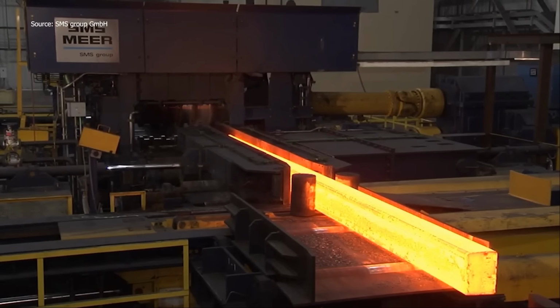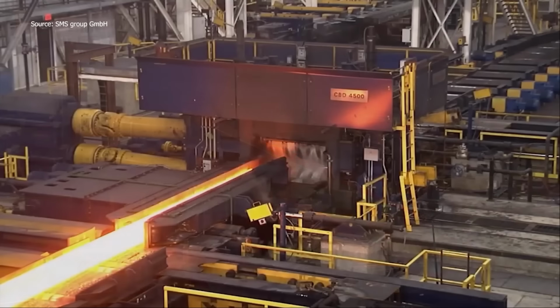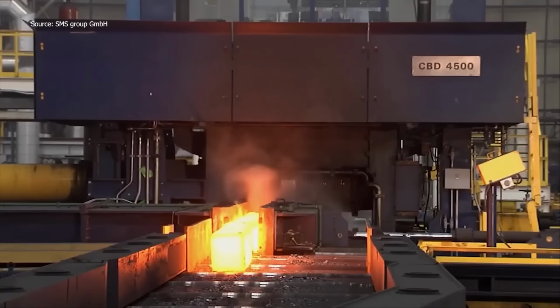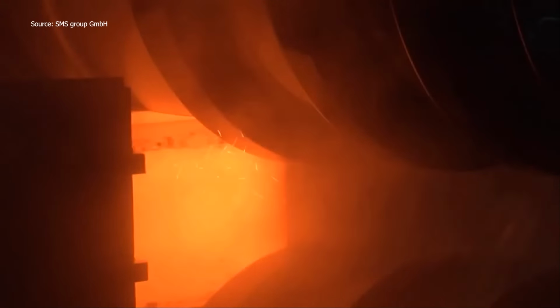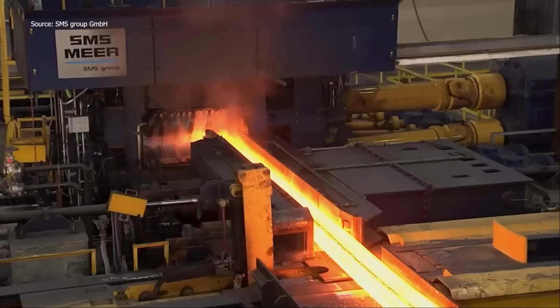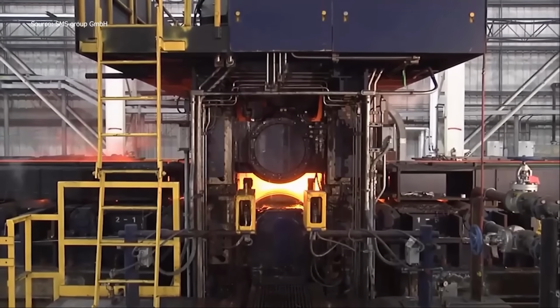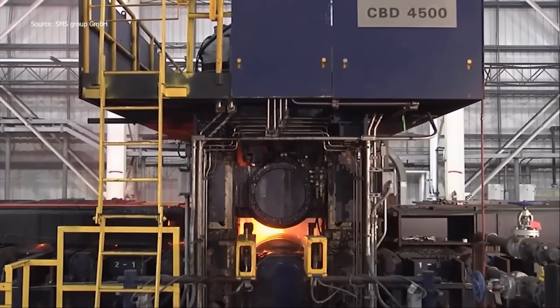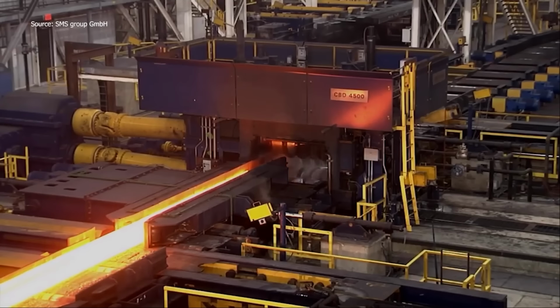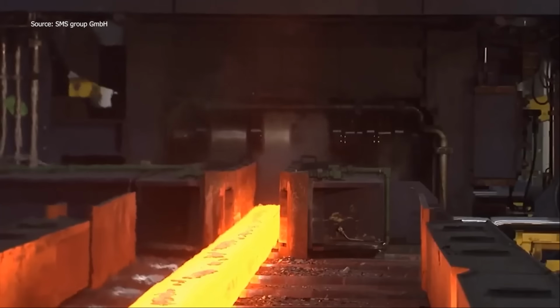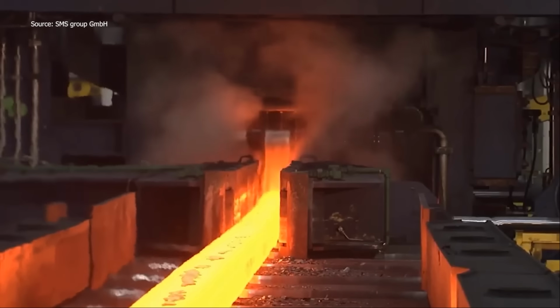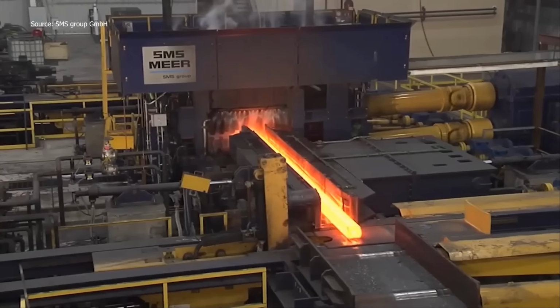It's a massive output, but every bar still demands tight process control. The process begins with billets heated to 1,100 degrees Celsius. After descaling, they pass through a compact breakdown mill featuring a 2-high reversing stand. A grip-type tilter rotates the billet between passes, reducing cross-section precisely. Each roll station uses different groove shapes to reach the target geometry.